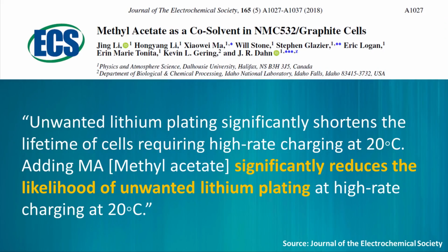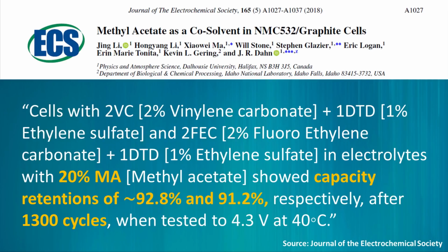Unwanted lithium plating significantly shortens the lifetime of cells requiring high-rate charging at 20 degrees Celsius. Adding methyl acetate significantly reduces the likelihood of unwanted lithium plating at high-rate charging at 20 degrees Celsius. They also mention, cells with 2% vinylene carbonate plus 1% ethylene sulfate and 2% fluoroethylene carbonate plus 1% ethylene sulfate in electrolytes with 20% methyl acetate showed capacity retentions of 92.8% and 91.2%, respectively, after 1,300 cycles when tested to 4.3 volts at 40 degrees Celsius.